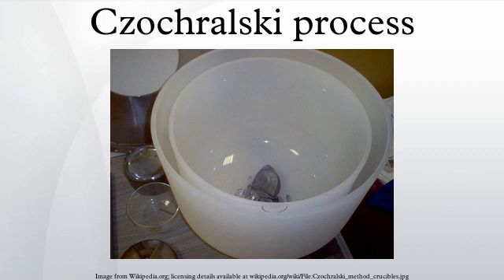When silicon is grown by the Czochralski method, the melt is contained in a silica crucible. During growth, the walls of the crucible dissolve into the melt and Czochralski silicon therefore contains oxygen at a typical concentration of 10^18 cm⁻³. Oxygen impurities can have beneficial effects. Carefully chosen annealing conditions can allow the formation of oxygen precipitates. These have the effect of trapping unwanted transition metal impurities in a process known as gettering. Additionally, oxygen impurities can improve the mechanical strength of silicon wafers by immobilizing any dislocations which may be introduced during device processing.